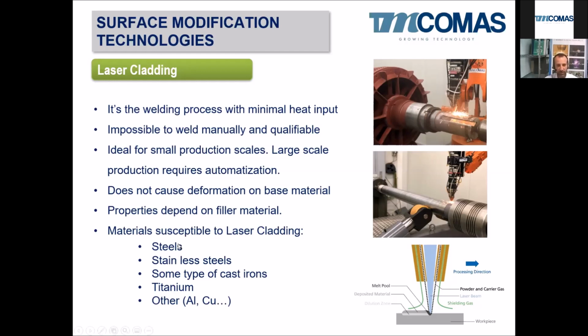What materials are susceptible to laser cladding? More or less the same as in conventional welding. So the weldability is very important. I would say the steels, having in mind that depending on the carbon content, it will be easier to weld or not. Stainless steels, some types of cast irons, titanium. We are repairing a titanium shaft for a customer with a titanium coating, without doing it in vacuum, just in open atmosphere with a special process with a lot of protecting gas. We can make claddings on titanium shafts.